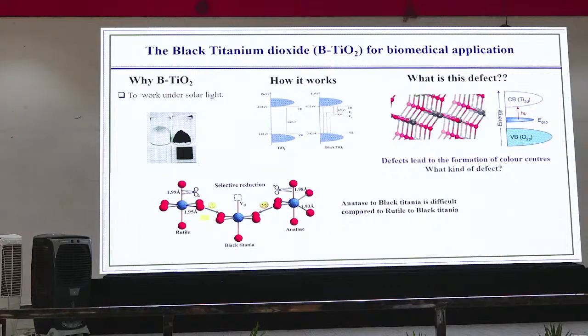So why does it happen? To identify that concept, I worked there for 2.5 months, and finally we were able to identify what exactly was happening. Usually when we irradiate with the pulse laser, it will take out some oxygen because we are hitting it with light. When we hit the TiO2 with light, from its phase arrangement, oxygen is removed. Since the oxygen has been removed, the neighboring titanium wants to accommodate its stability. To do that, it is reduced to its Ti3+ state. These Ti3+ states and the oxygen vacancies together usually form a new energy level, a new energy position, from where the electron transition will happen. That is why it turns black.